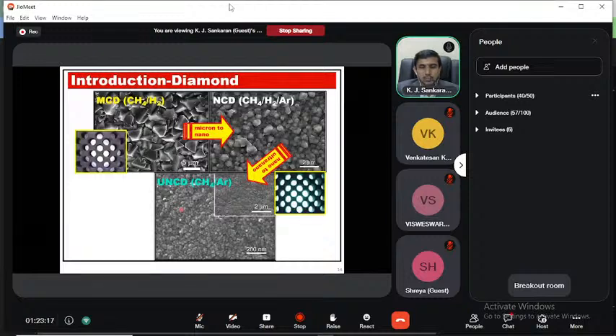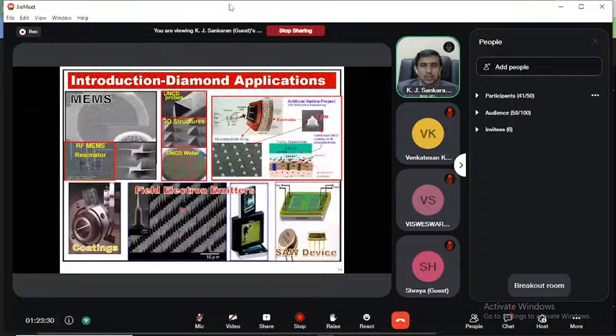So these UNCD films have a very smooth surface, and the grains are really 5 to 10 nanometer as compared to microcrystalline diamond. This smooth surface is applicable for various applications like microelectromechanical systems, and we can also coat UNCD on probes, 3D structures, UNCD wafers, surface acoustic wave devices, and also uniform coatings on bearings. An artificial retina project is still ongoing at Argonne National Lab to make UNCD for the artificial retina and field electron emitters.